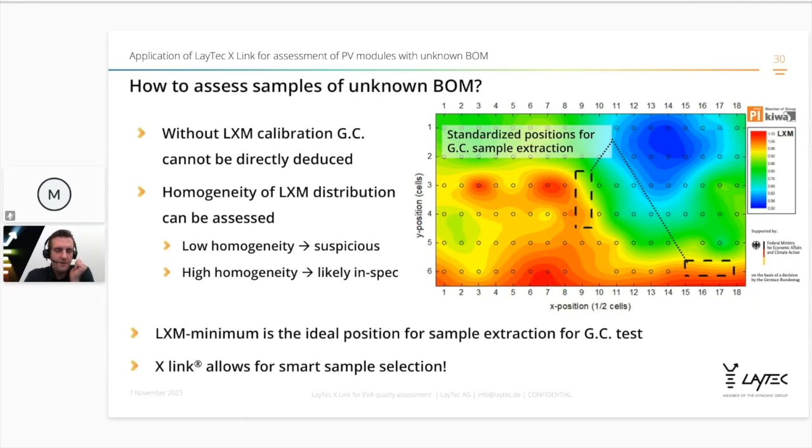These were the areas where the material was usually cut out and sent for Soxhlet testing. And this, of course, is a very nice example, because it shows that you're really playing a lottery here. In that case, the cutout pieces, just by coincidence, resemble the most well laminated areas. So you would probably get a very good result of 1 point something from your chemical testing, but you would completely miss out on this part, which will be critical in the field.